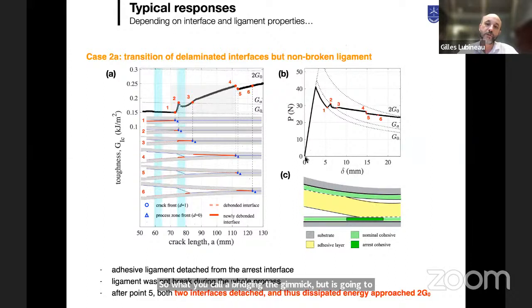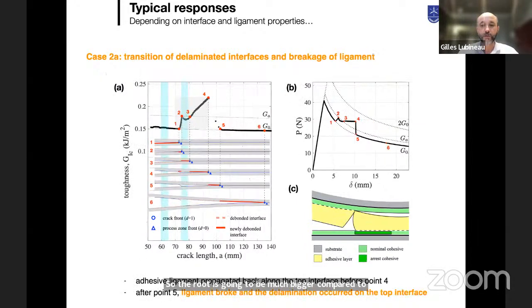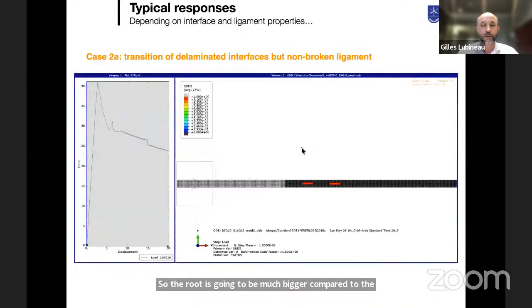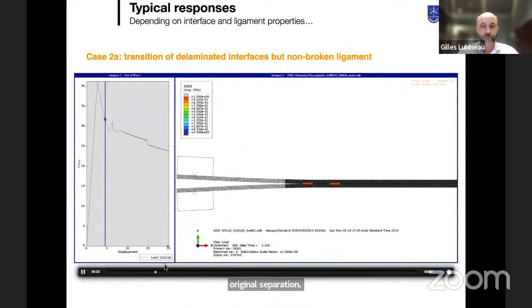And in this case, of course, this is going to modify the delamination curve a lot, because at the beginning you follow the classical delamination curve when you delaminate on the bottom. But as soon as you create this ligament, you are going to store a lot of elastic energy, and you are going to stabilize your delamination curve. So the load is going to be much bigger compared to the original separation. So this is something, when you look at the simulation, that means that you get something like this.